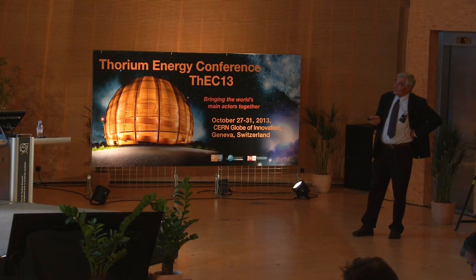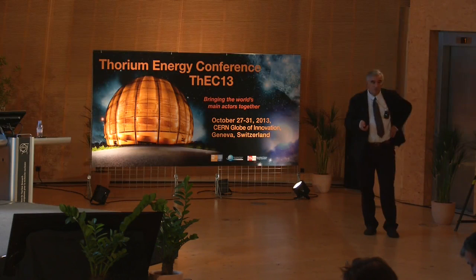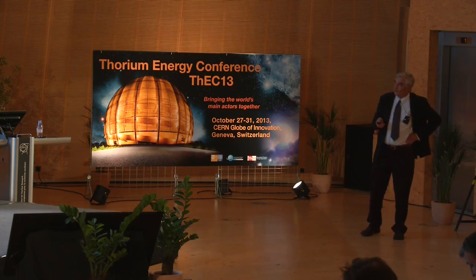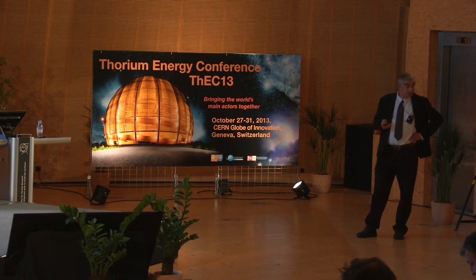There was also an analysis of the radionuclides present in the gas. We have a good agreement with the previous calculations, because the team in charge of neutronics had to make a prediction of the contamination of the gas, which was produced by the irradiation.